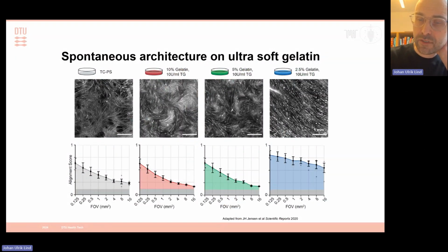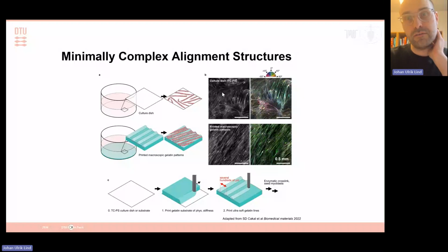So we were interested in saying, if we now use these soft materials, can we get away with just very small cues? So rather than print features that are, say, 60 micrometers in size, we were interested in studying if we just print alternating patterns of different mechanical properties of gelatin, can we induce this overall organization of the skeletal muscle fibers, but without having to go very small in feature size. So essentially, we were studying what happens when we print now in steps of hundreds of micrometers and big filaments, which is obviously a lot easier and more scalable to do.